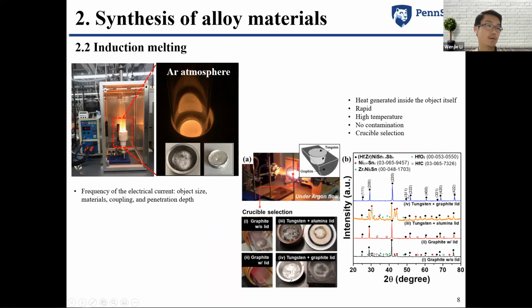When we prepare these half-Heusler materials using induction heating, we also find that how uniform or single-phase the product is also relates to what types of crucibles are used. When we use only graphite, loading the raw materials in the graphite crucible without any lid on top, we get a lot of annoying impurity phases. With the lid on top, we get mostly the desired half-Heusler phase, but still cannot avoid the impurities. Then we tried using another crucible inside the graphite boat, both tungsten and alumina. The combination of graphite and tungsten provides the best results for induction melting of the desired half-Heusler phases.